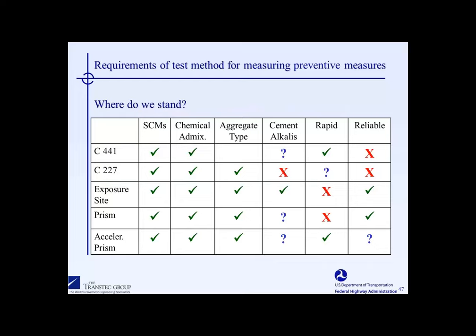During the course of the presentation today, I went through a variety of different test methods, and now we just have a little box to check off how close we're getting to that reliable and ideal test. You'll see here that tests like 441 and 227 are unreliable for the reasons I discussed. The exposure site is quite reliable, but unfortunately, it's very difficult to establish an exposure site, to have the resources and the space, and it takes a long time to get expansion of outdoor specimens. It might take 5 years, 10 years, or even 20 years. So it doesn't quite meet the requirement for rapid testing.